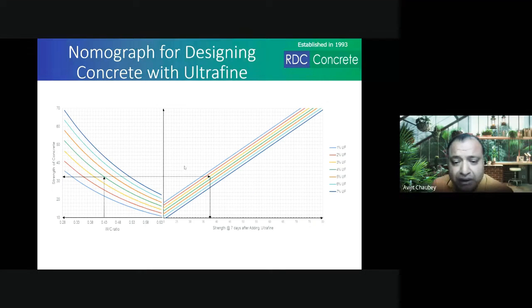Now this is the nomograph that we have made for designing the concrete with ultrafine. As I told you, the left hand side of this graph is the same equation that I had shown you earlier. It is the same equation that I've published in my book, for different strengths of cement. Now at 0.43 water cement ratio, let us say you get a strength of 32 MPa. How do you use this nomograph? Let us say you have your trial data: at 0.43 water cement ratio, you do the trial and you are getting a strength of 32 MPa.